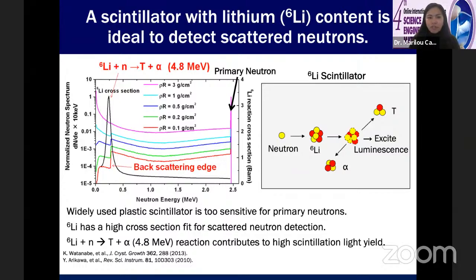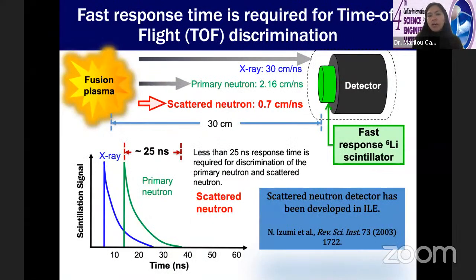So that's the first consideration for developing the scintillator. There should be a high lithium-6 content, but we should also take into account the response time of the scintillator. So we measure the scattered neutrons using the time of flight measurement technique. Essentially, if this is your fusion plasma, we place the detector at a fixed distance from the plasma chamber. In this case, for example, 30 centimeters away from the plasma chamber. In the fusion plasma, X-rays are generated as well as primary neutrons and scattered neutrons. And these three have different speeds. So they travel at different speeds. X-ray is the fastest, while scattered neutrons are the slowest.